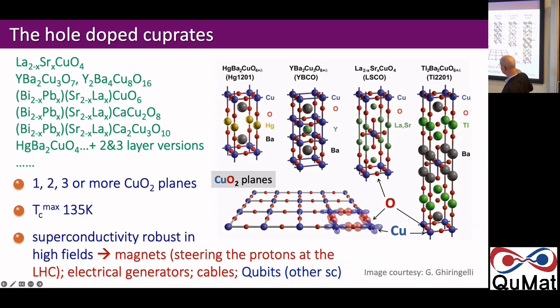The highest TC at ambient pressure is 135 Kelvin. If you put it under pressure, it goes to 150. So for us as physicists, it's half of room temperature, right? So we're halfway to room temperature superconductivity, at least if you calculate in Kelvin. So this kind of superconductivity is a huge theoretical challenge. The Nobel Prize for the discovery of the materials has been given, but still none for the theory behind this. So a chance for some of you here.